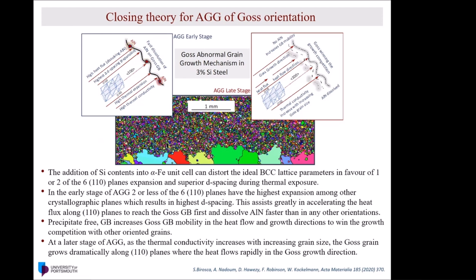So what we have to distinguish, and what our solid conclusion is, is the early stage of the abnormal grain growth and the late stage of abnormal grain growth. So many grains on the edge can grow normally, but only growth rate is predominating, and that's related to two factors. The addition of silicon is distorting that unique high symmetrical unit cell of the BCC structure for iron, and that's causing